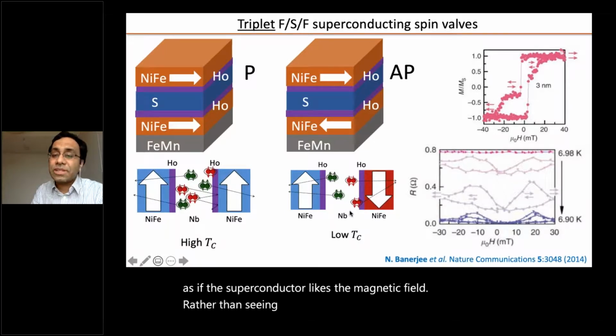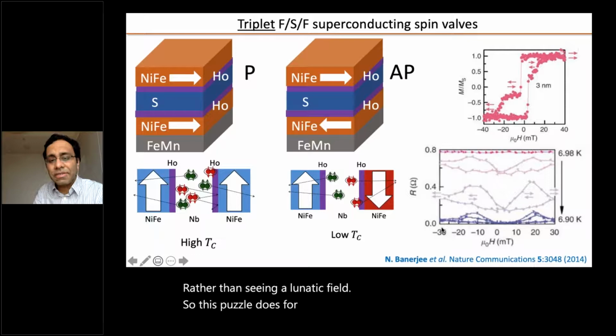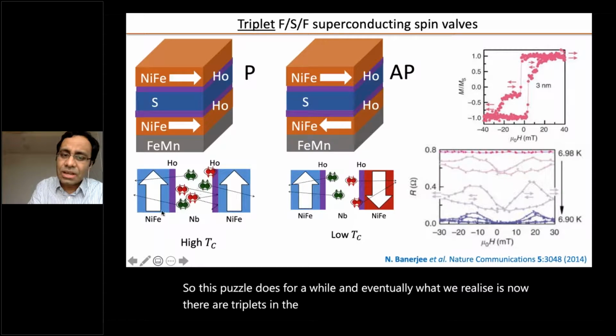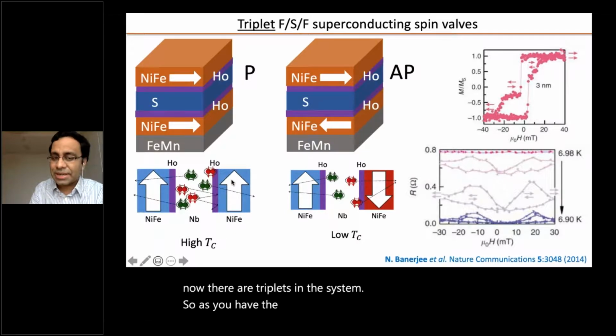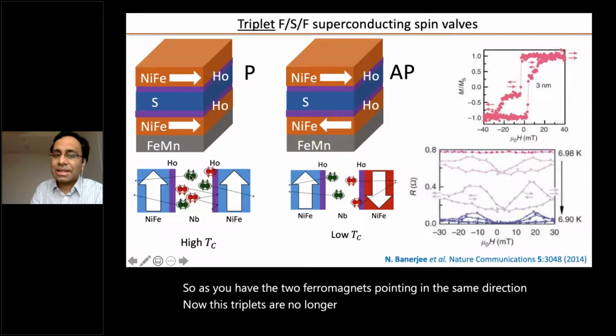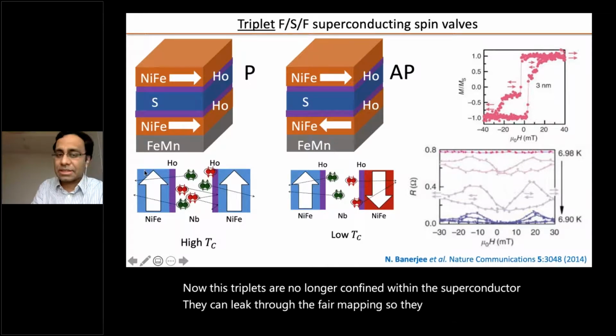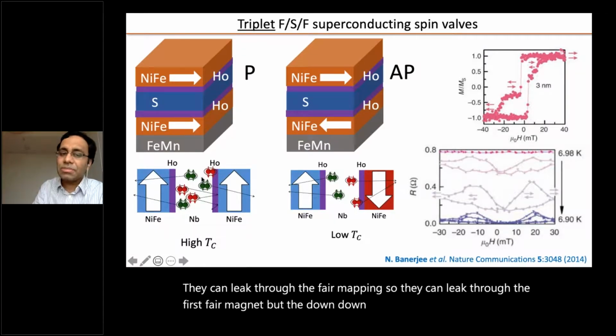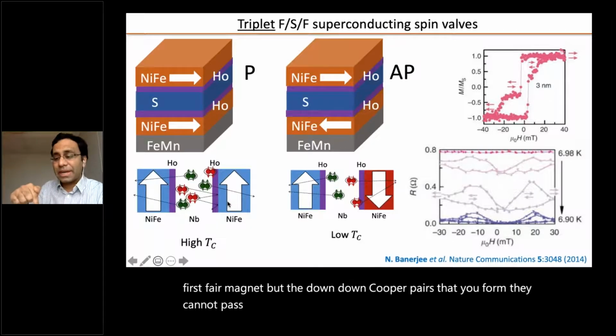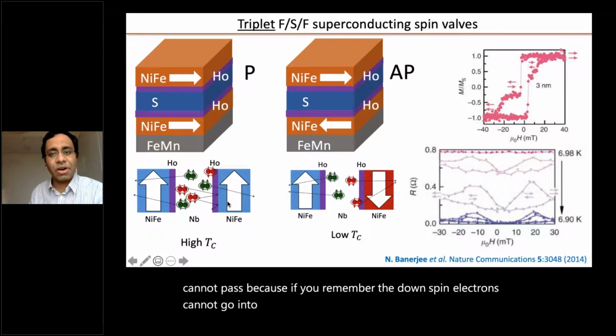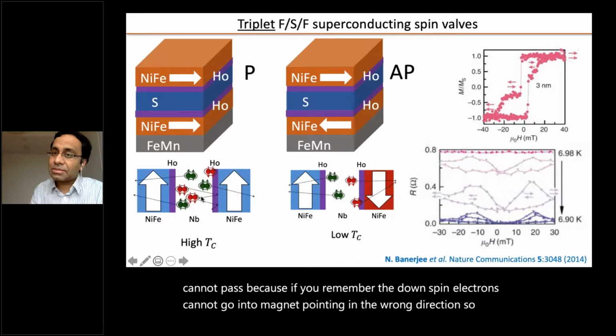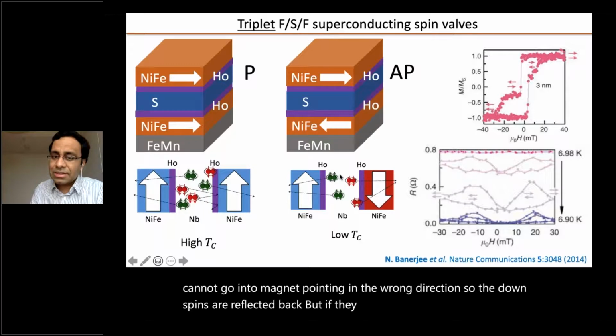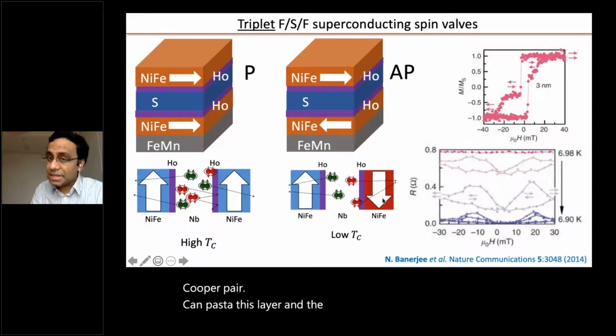This puzzled us for a while, and eventually what we realized is that now there are triplets in the system. As you have the two ferromagnets pointing in the same direction, these triplets are no longer confined within the superconductor. They can leak through the first ferromagnet. But the down-down Cooper pairs that you form cannot pass, because if you remember, the down-spin electron cannot go into a magnet pointing in the wrong direction. So the down spins are reflected back. But if they are anti-parallel, then the up-up Cooper pairs can pass through this layer, and the down-down Cooper pairs can pass through this layer.